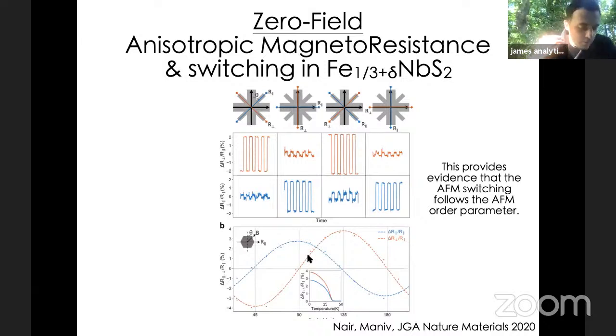So the reason why I bring this up is because the anisotropic magnetoresistance will become, in some sense, an independent measure of what we're doing to the Néel order that I'll come back to in a second. Okay, so that's one of the punchlines. We have this nice intercalated TMD. You can switch it like an antiferromagnetic switch by applying these relatively low current density pulses, and it seems that you're doing what the theory tells you should be doing, which is rotating the average Néel vector.